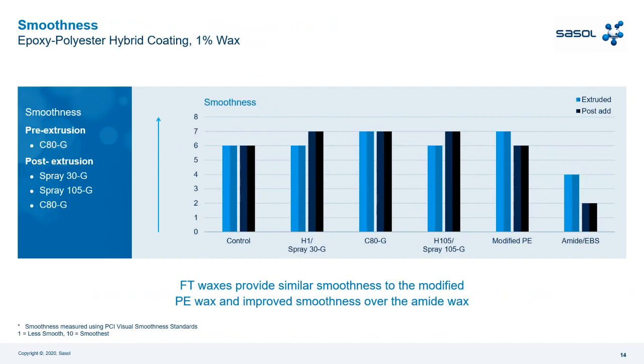Then smoothness, again a pre-extrusion and a post-extrusion test. The control, you need to see the highest value is the best. So C80G achieves a good result in pre-extrusion, and it's quite similar to the modified PE, the HDPE. In post-extrusion, we have Sasol Wax Spray 30G that achieves the best result for Sasol Wax, and also similar to Spray 105G, and the best result with respect to the competition. So this is for smoothness.